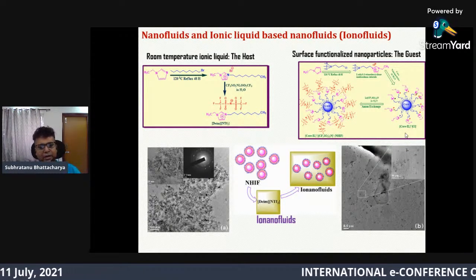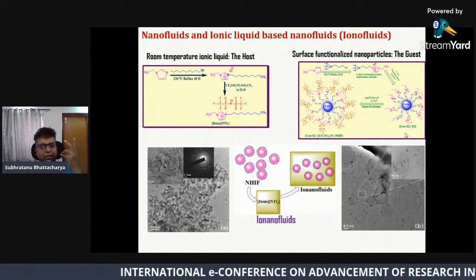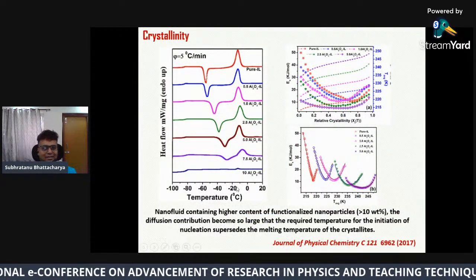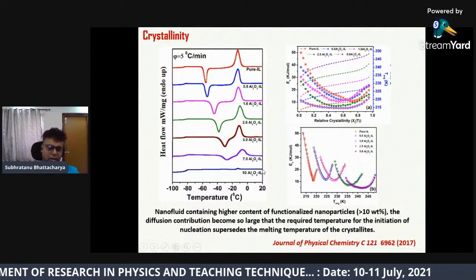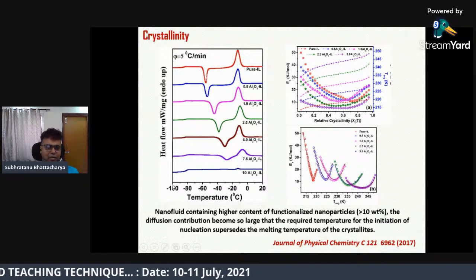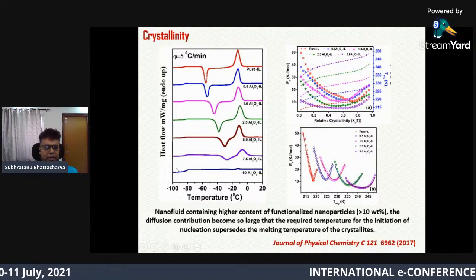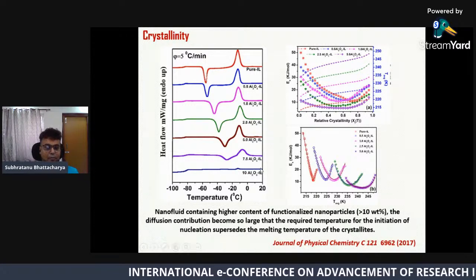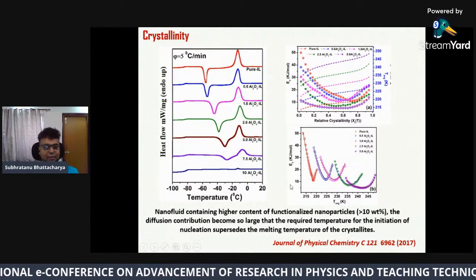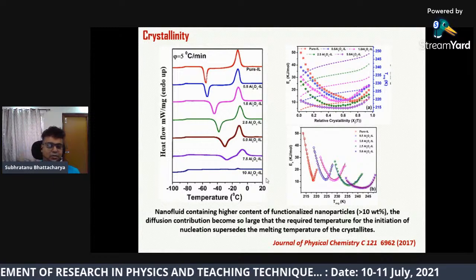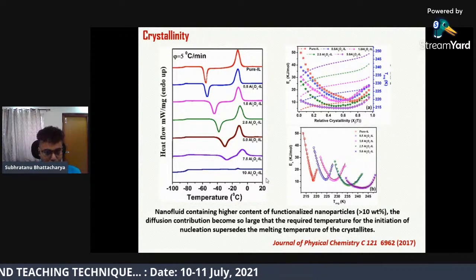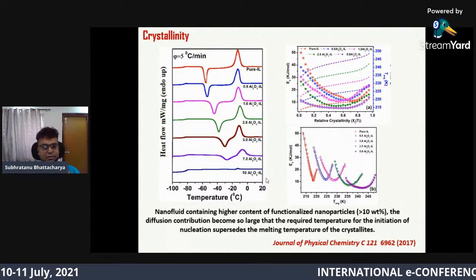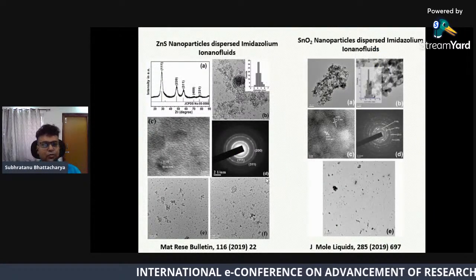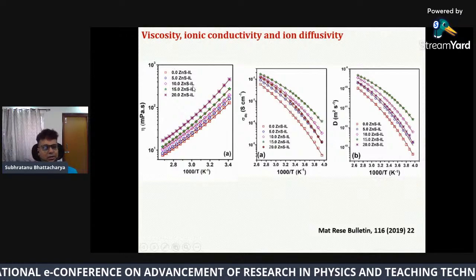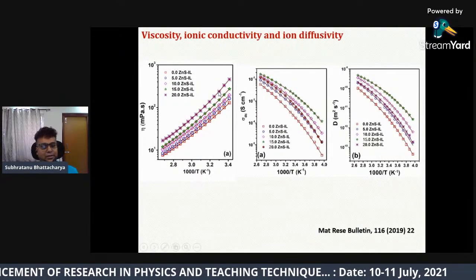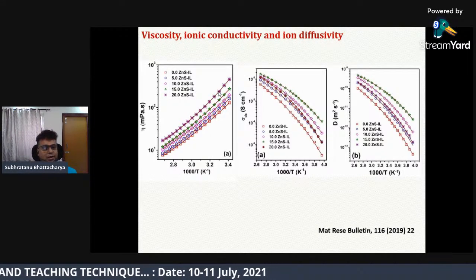But what we got was that even with increasing viscosity, we are getting very high conductivity. These are DSC plots, which only those who are aware of it can understand. This is the crystallinity graph, and after some time we saw that we got the ionic liquid completely amorphous instead of crystalline. This amorphosity arises due to the incorporation of surface functionalized nanoparticles. And these surface functionalized, ionic liquid based amorphous nanofluids show beautiful properties: even if you increase the viscosity, their conductivity increases up to a certain extent. Their conductivity does not fall with the increment of viscosity.